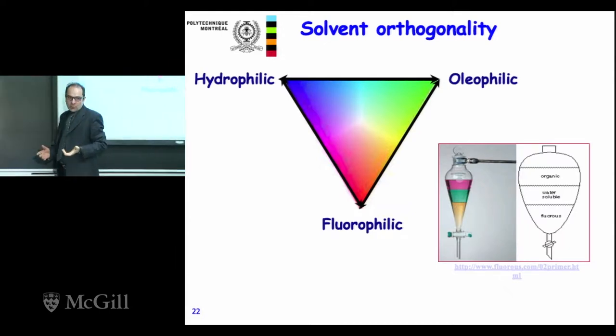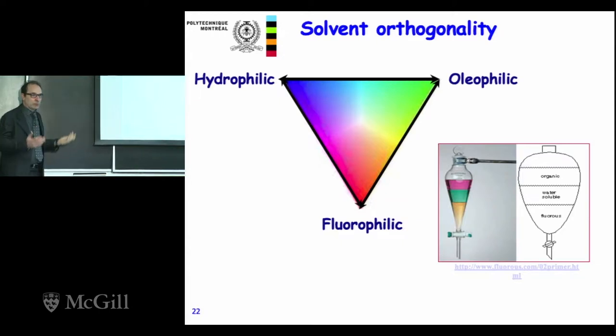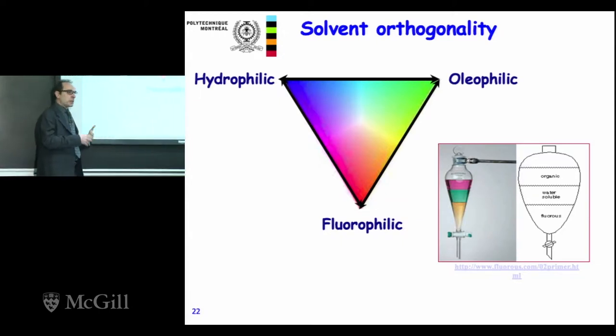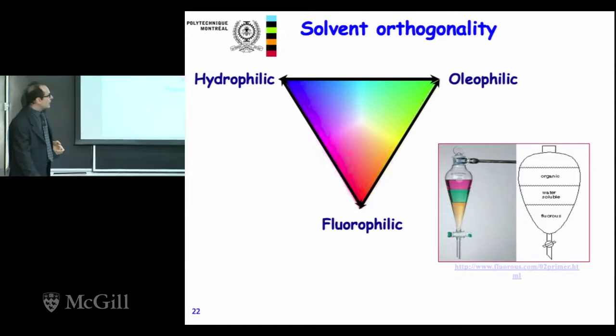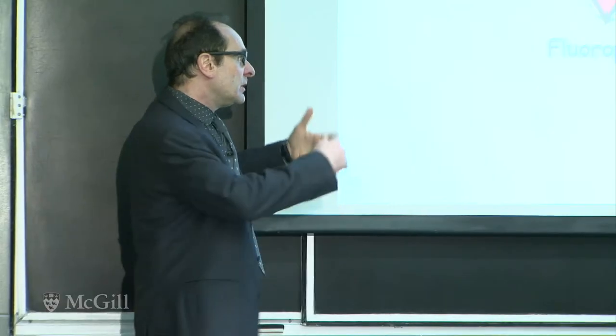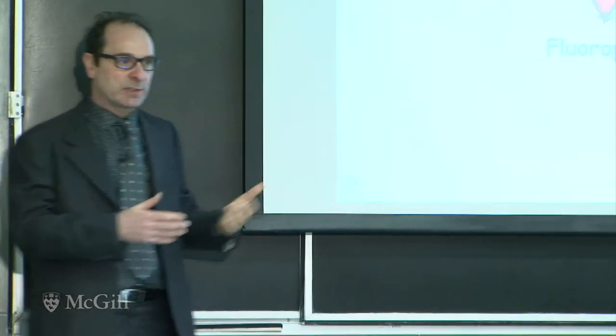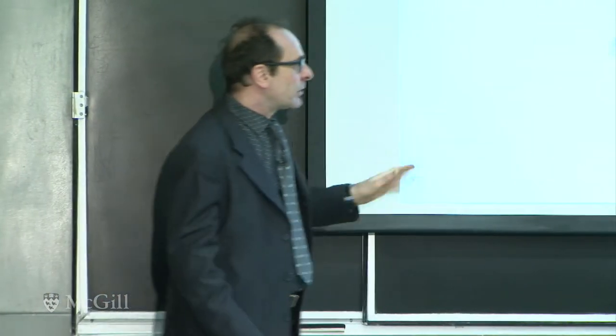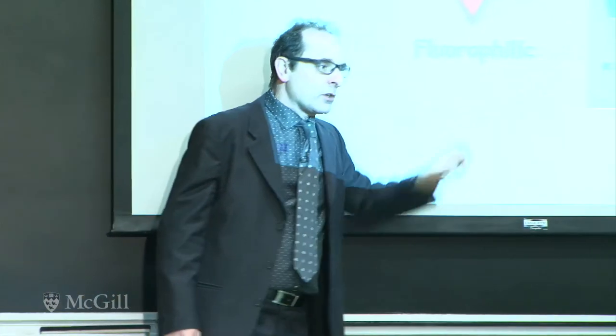We can use exactly the same equipment because we just use the same photolithography equipment. We just have to adjust the lithography parameters like the exposure time, etching time, and the developing time. So actually, all the patterning we do on these materials is now done with this product line, which is sold by a company called Orthogonal, which is based in Rochester, New York.